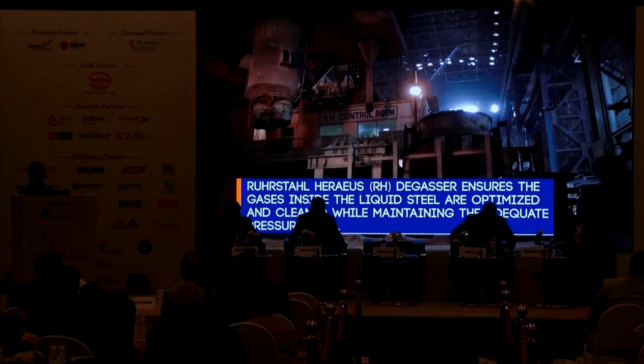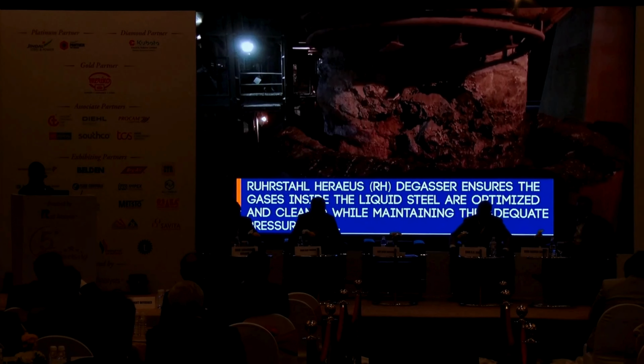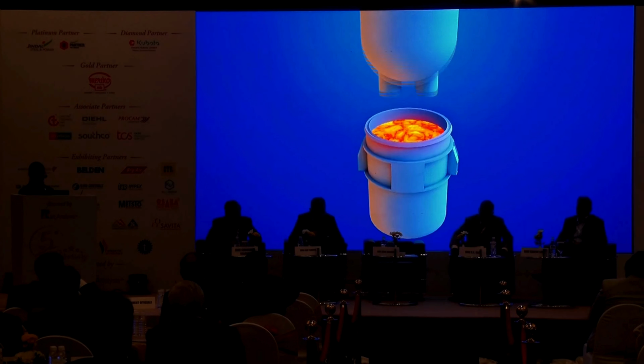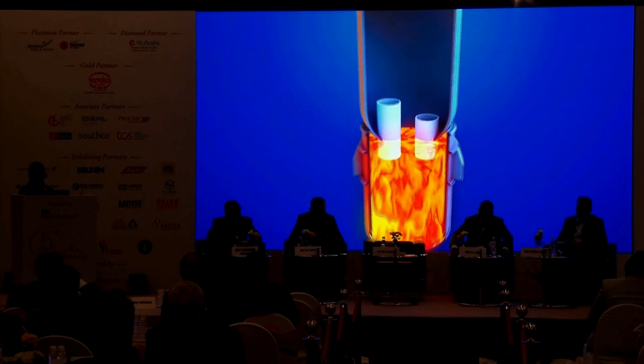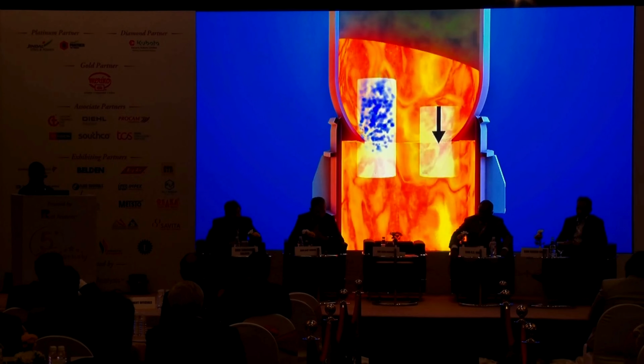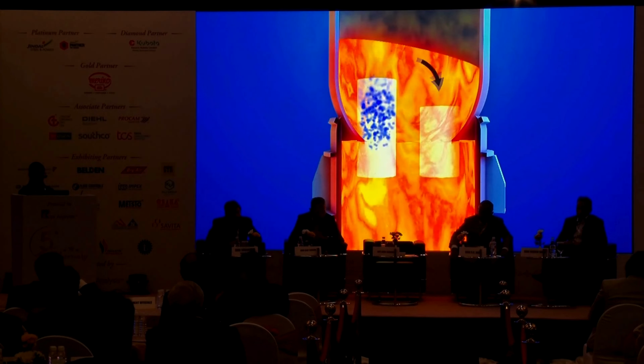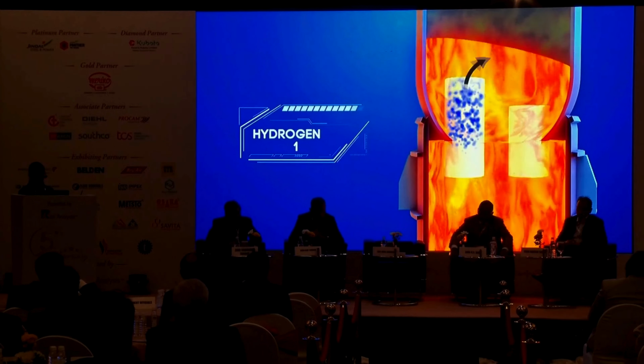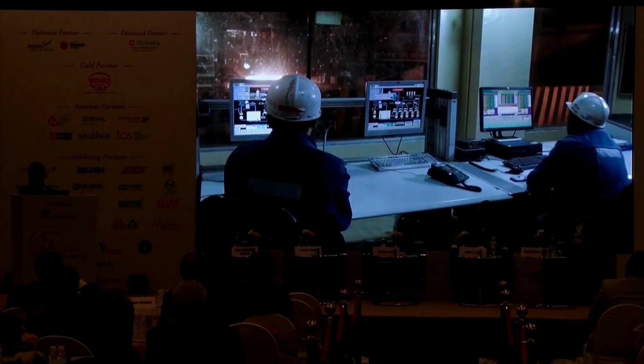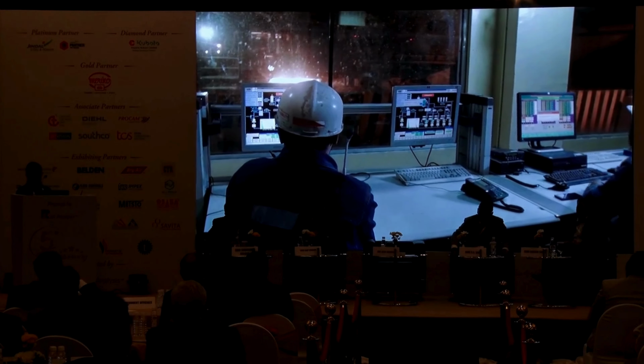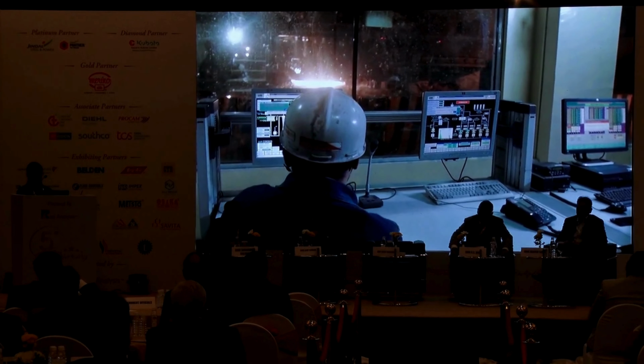and superior metallurgical traits. Gases dissolved in steel may have high detrimental effects like shatter cracks during usage and must be controlled in very close limits. At JSPL, Ruhrstahl Heraeus RH degasser is used for cleaning steel from dissolved gases like hydrogen, oxygen and nitrogen. In RH degassing, pressure inside the liquid steel is reduced to less than 1 mbar, while ensuring that the hydrogen content is less than 1.6 ppm, as specified in IRS T12-2009 rail specifications.